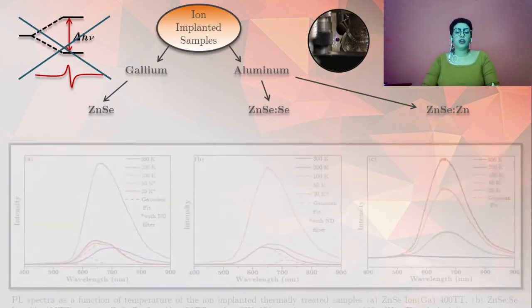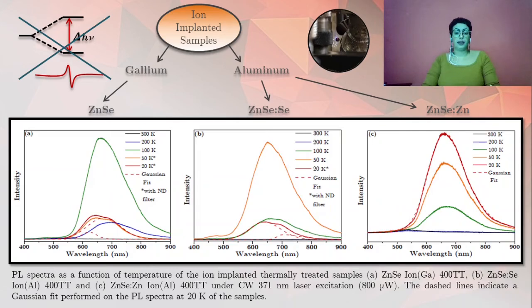EPR measurements were also performed, but no spin-resonant transitions were observed. In the PL measurements on the ion-implanted sample doped with gallium, it is possible to identify two luminescence bands by the Gaussian fit of the PL spectrum measured at 20 Kelvin. The band centered at approximately 623 nanometers is also present in the diffusion gallium-doped sample.